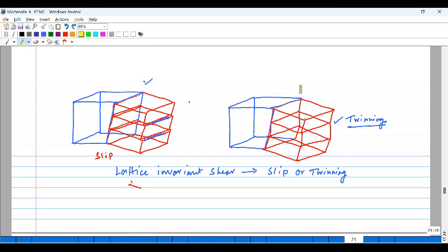Okay. Moreover, as you can see from these diagrams, the habit plane, which is here, and here, is corrected for the distortion by the lattice invariant shear, but it is a plane of zero distortion only on a macroscopic scale. Okay, and therefore the indices could be irrational numbers. Okay, you can see the same thing from the following schematic as well.